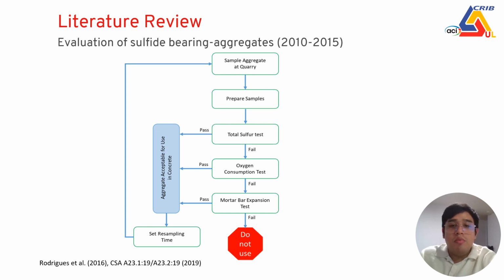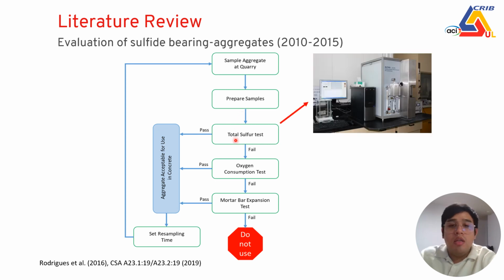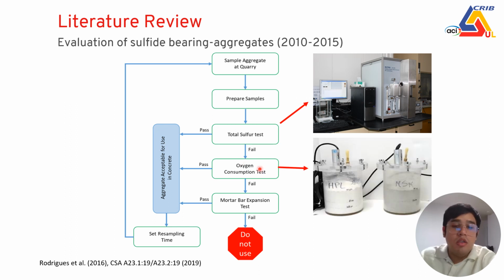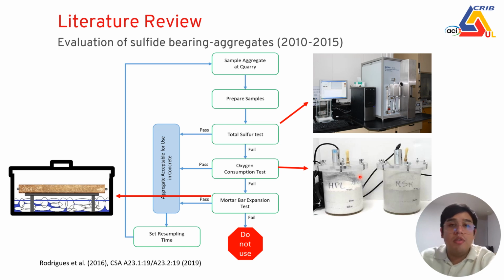So the first step is to prepare the samples, and after the samples are prepared, there is a total sulfur test that is to quantify the sulfur in the aggregate, and then there is an oxygen consumption test that is to see how the oxygen is consumed by this type of aggregates. And finally, a mortar bar expansion test where we measure the expansion to see how these products will be created in different conditions. So there are two different conditions in this mortar bar test. One is the oxidation with high temperature and low relative humidity, and the other condition is low temperature and high relative humidity.